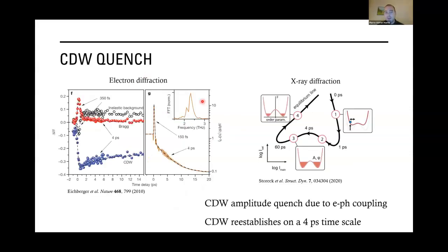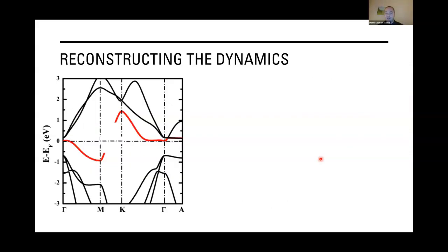But if we compare this result with what has been observed with electron diffraction and X-ray diffraction, the re-establishment of the charge density wave gap takes this 4 picoseconds. So we have built a complete picture of the dynamic inside this material.